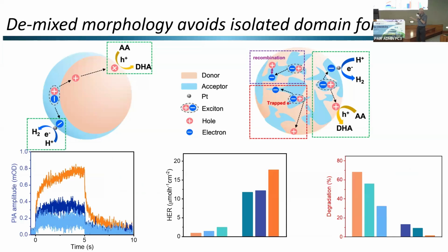And what we can see firstly is that when we have this broken core shell type structure, we get much higher photocharge generation. So we see this from the PIA spectra, much higher rate. So these are three donor acceptor systems that form broken core shells, and these are three that form intermixed. We see the rate is much lower in comparison to these systems. But really interestingly, the three low rates are also degrading much faster. So you see this degradation over, I think this is 24 hours, constant irradiation. And the reason for this is that most organic acceptor molecules are unstable in the presence of excited electrons.